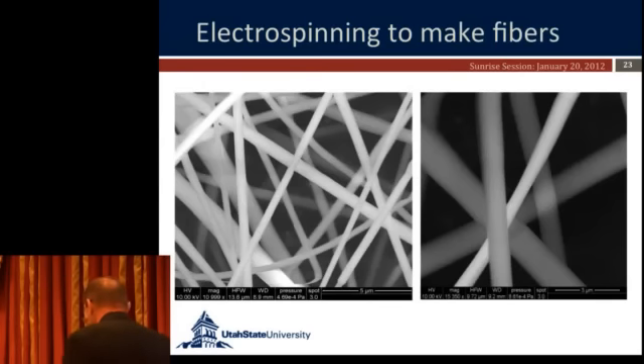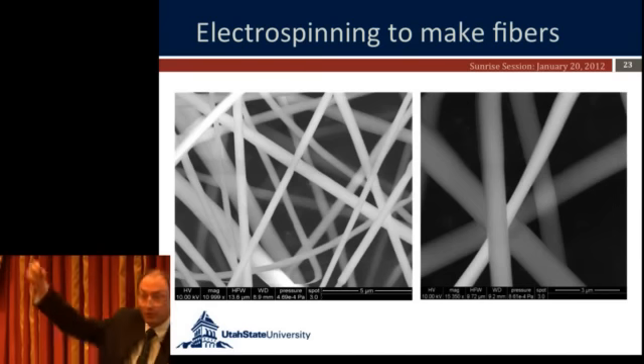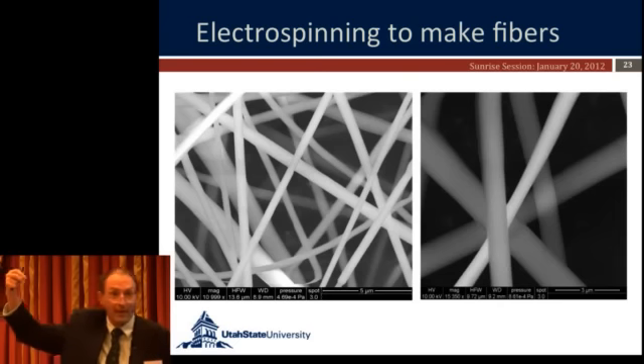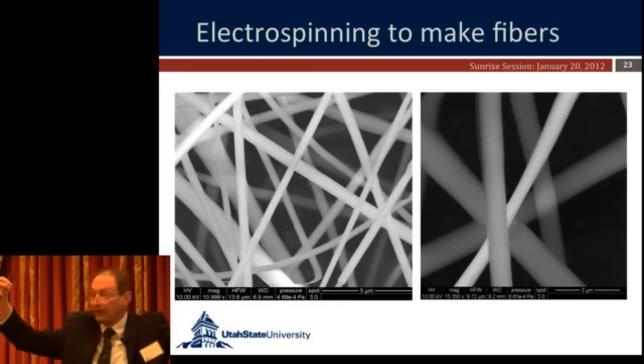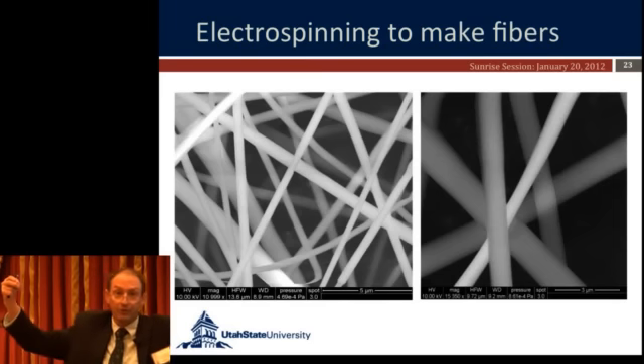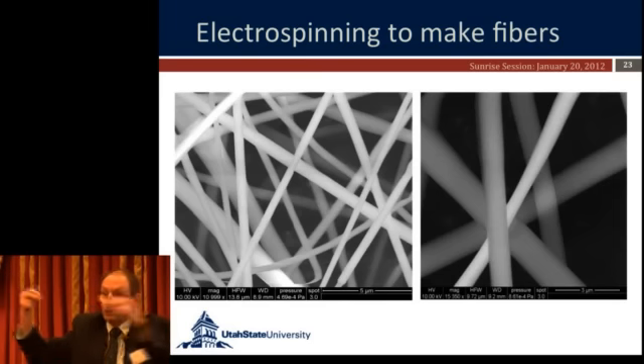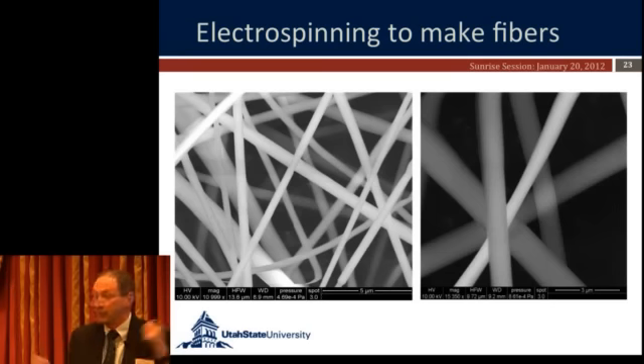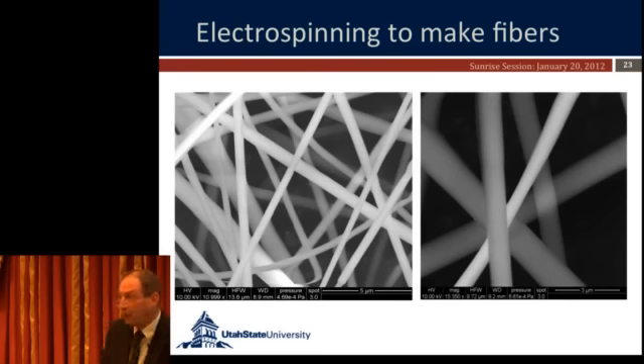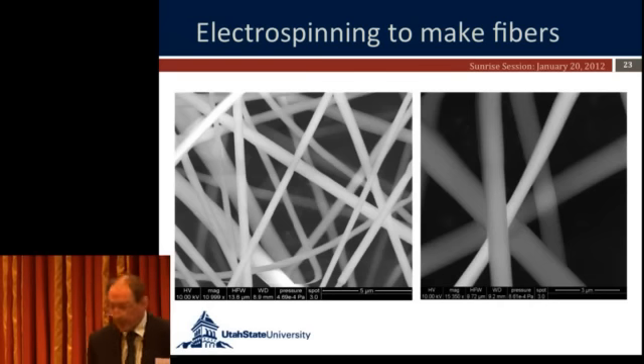Now, we tested with a collaborator at the University of Nebraska another way to spin fibers. It's called electrospinning, and it's really pretty simple. You take your solution, put it on one pole of a battery, and put the other pole over here, and you just keep jacking up the voltage until finally, just exactly like you expect, a spark shoots across there, except instead of a spark, the silk protein shoots across there as a liquid. What you typically see happen when you do that is this. You end up with a mat.